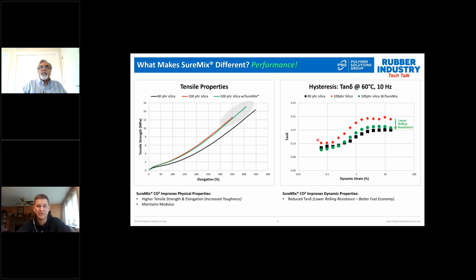By using SureMix in this compound, we're able to improve the elongation and improve the tensile to get to the level of tensile that's expected by having the degree of dispersion in the 100 part silica compound that we had in 80.